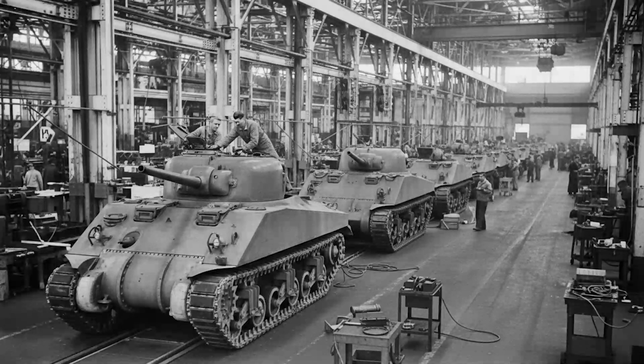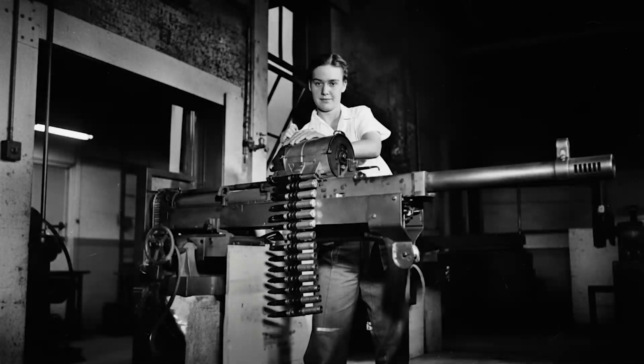However, the welded hull program faced challenges that threatened to undermine its effectiveness. Production schedules slipped as welding facilities encountered quality control problems that had not appeared during prototype construction. Some welds failed inspection due to incomplete fusion, hydrogen porosity, or stress cracking that appeared during post-weld heat treatment. These failures required rework that slowed production and raised questions about whether welding techniques could achieve the consistency required for mass manufacturing.